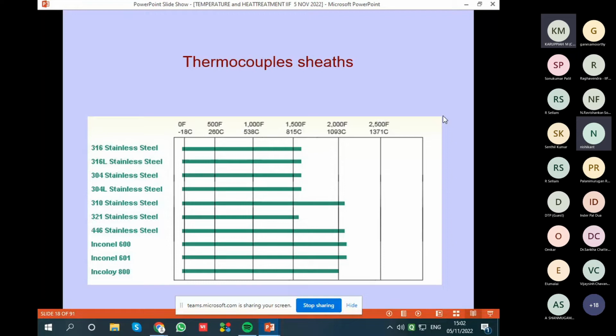And stainless steels, if you want to use, then you have to use the proper 304, 316 or 310, depending on the heat treatment job, whether it is a salt bath or atmosphere, all those tables and details are available. Depending on that, you should use it. Again, I'll repeat, whatever sheath you want to use, always use a sheath of the higher range so that the sheath gives a longer life. So Inconel 600 is better than, say, SS310 or SS304, because it lasts for a longer time.